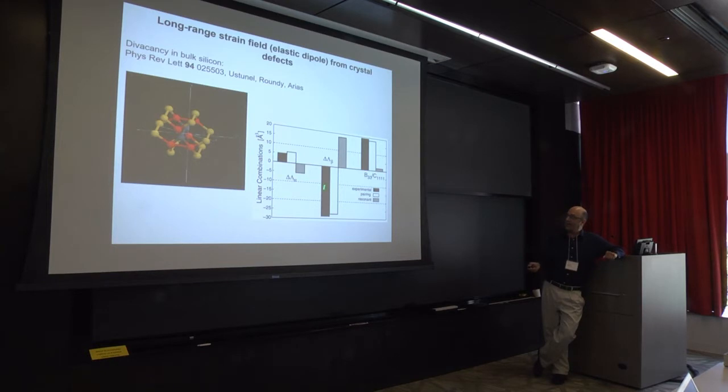So the experimental data for various components of this tensor are given in black, and our calculations for the two competing structures are given in white and gray, and we were very clearly able to distinguish one proposed structure for the defect from the other. More importantly, notice again the accuracy of how this fairly subtle effect we can calculate directly, again from first principles.